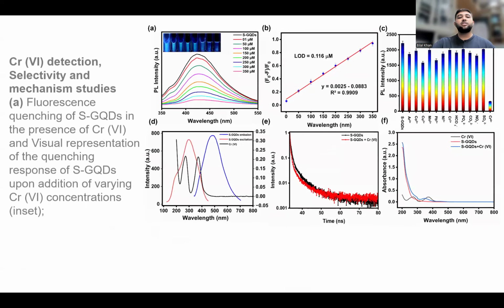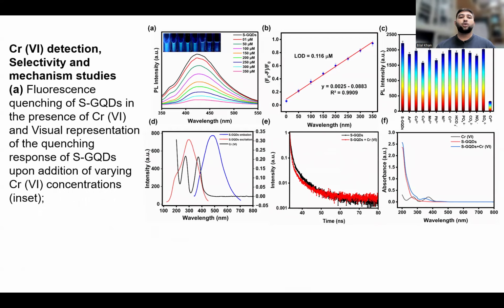After that, we did the application for chromium-VI detection. In A, the inset shows the visual representation of the fluorescence quenching of chromium-VI by the sulfur-doped graphene quantum dots. And we used a long and wide range from 1 micromolar to 350 micromolar.